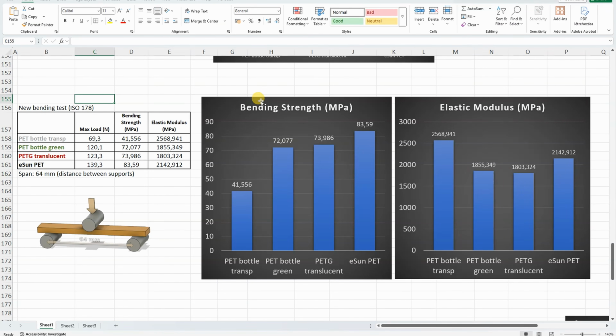The bending strength is calculated from the maximal load, and by far the weakest is the transparent PET. The other three are more or less similar. Of course, the strongest is the eSun PET.